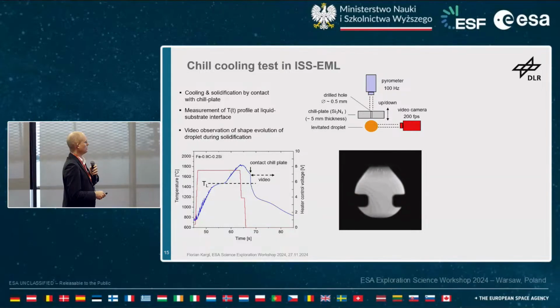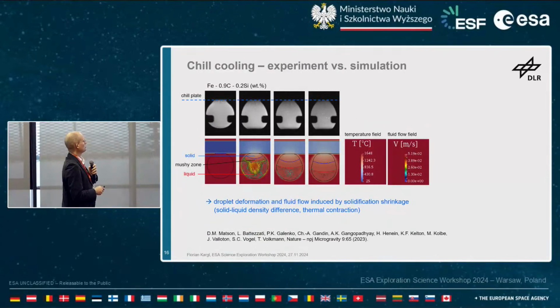So chill plate is contacting, sample starts to solidify, so you see the growth of the crystals here. It's deforming and yeah, fully solidifying. So and then, of course, this observation that one has in the experiment could be matched with the model that the colleagues from Sophia Antipolis developed at MINES ParisTech, and they described here in the model fluid flow induced and temperature evolution of the sample, shape deformation, and so on.